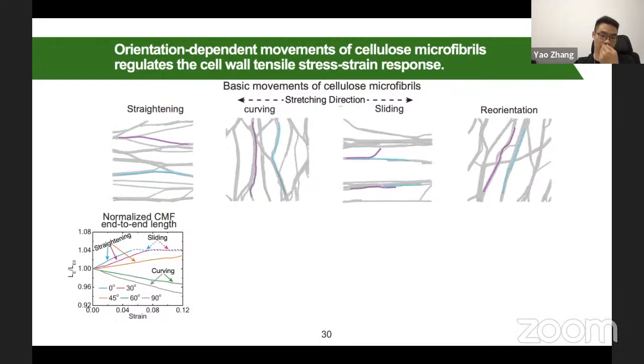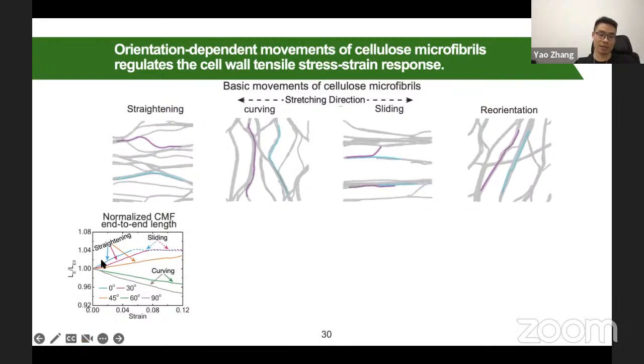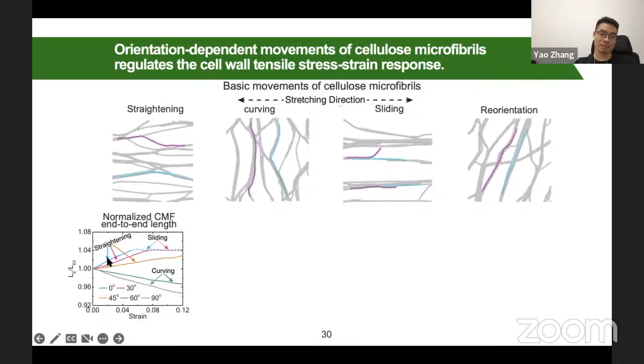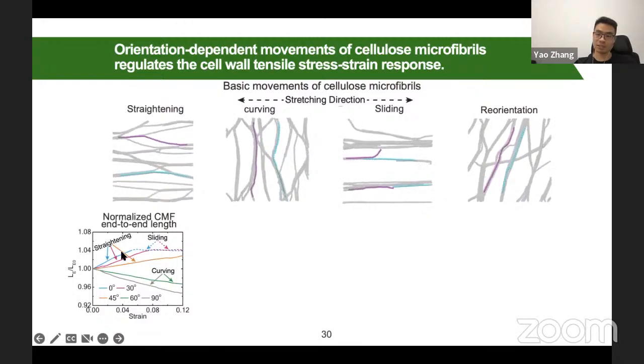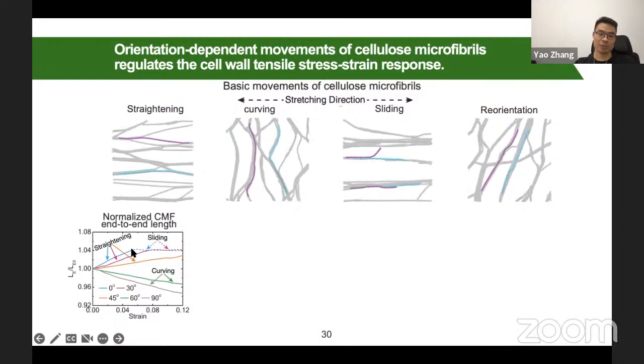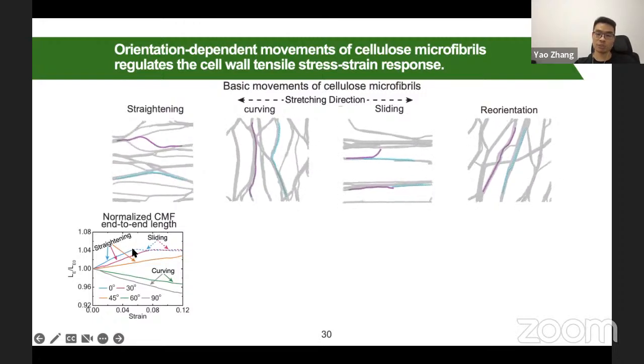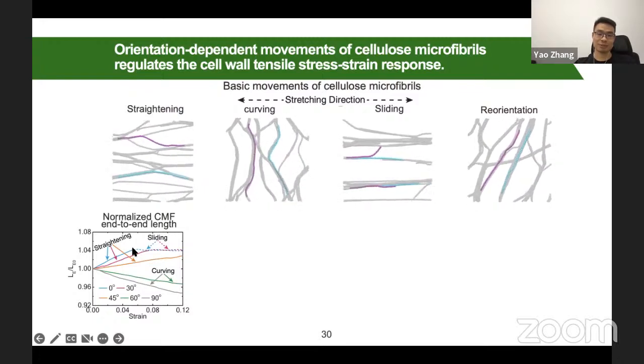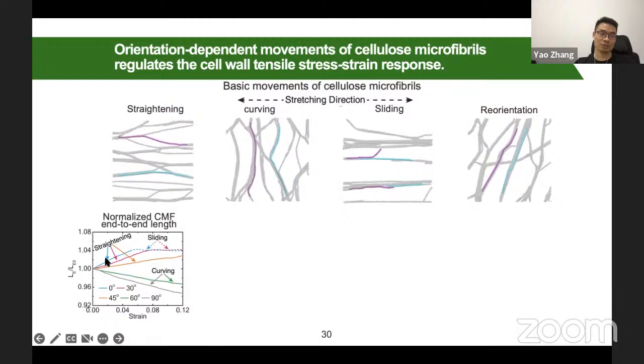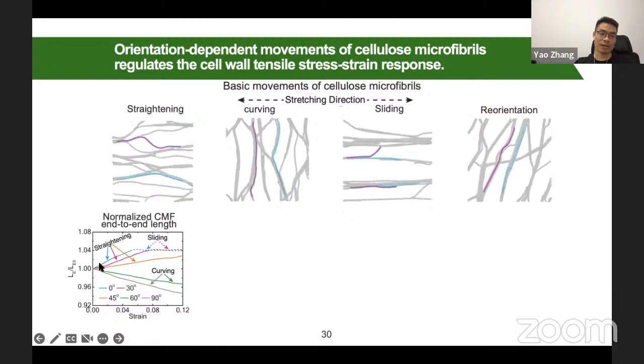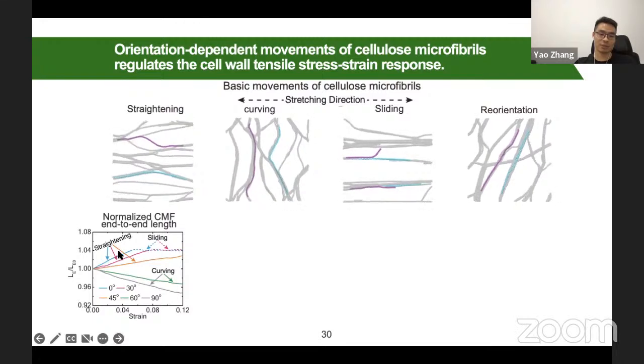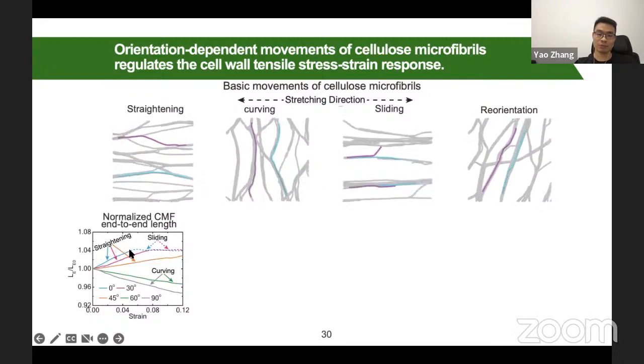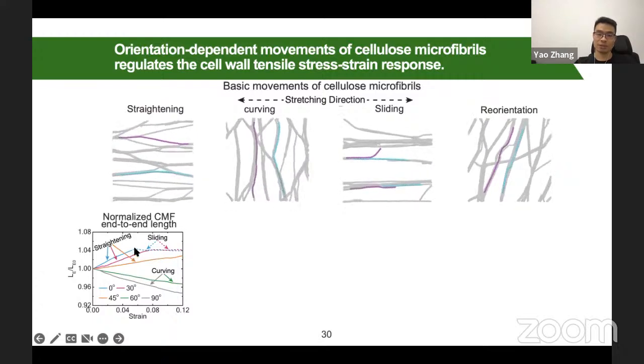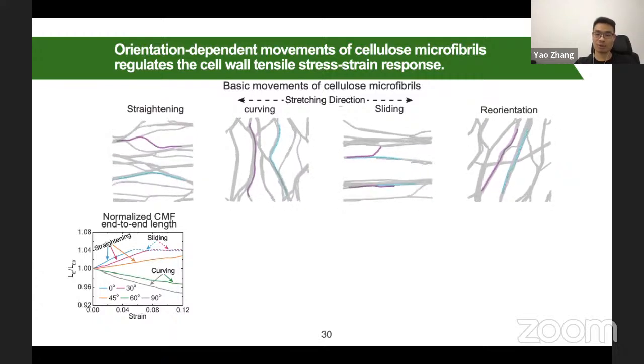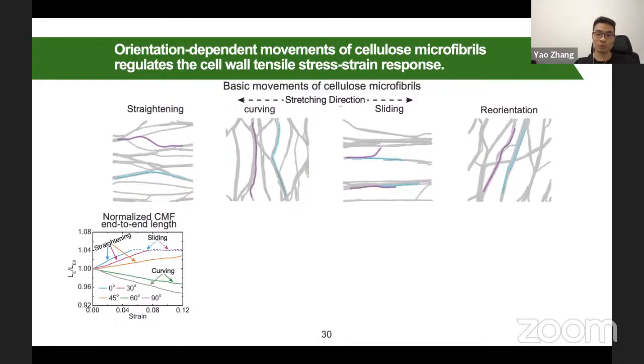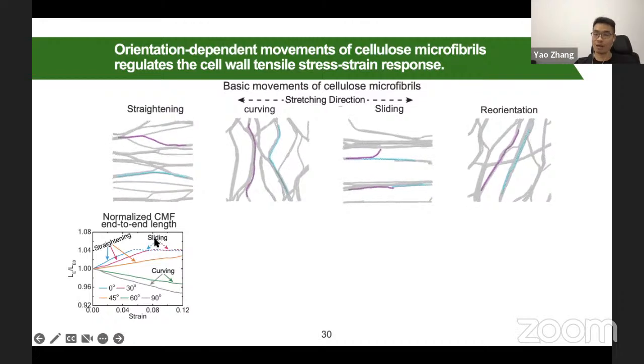So what will happen? If you look at the blue line, you can see that the end-to-end length will first linearly increase, and then it will reach a plateau. Once it reaches the plateau, we mark it with the dashed line. When the end-to-end length increases, we call it straightening. When it reaches the plateau, it means that the end-to-end length of the fiber will not change. So what will happen in that case? Sliding will happen.